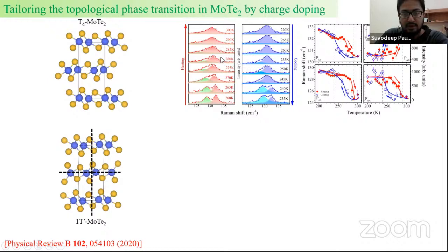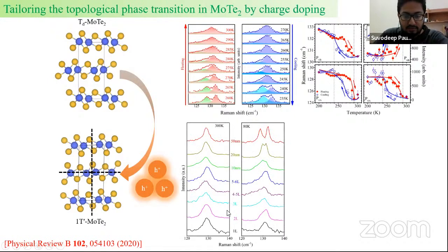So basically this phase transition may be seen through Raman as a hysteretic change in phononic properties around the phase transition temperature, which appears at around 260 kelvins. So interestingly, what we see here is that for the very thin layers, if we recall from the previous slide that the thin layers were hole doped, the thin layers do not undergo a transition to the Td phase even at low temperature, which is to say that the hole doped samples are stabilized in the 1T prime phase.